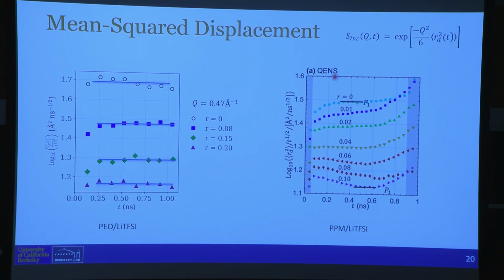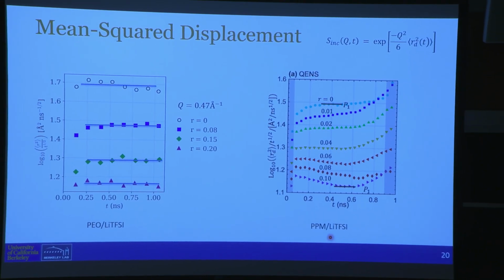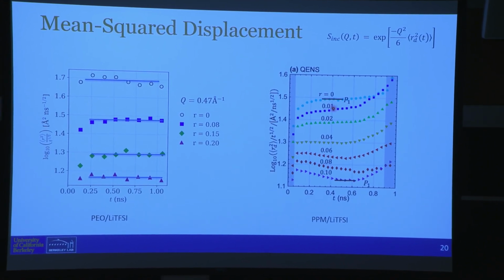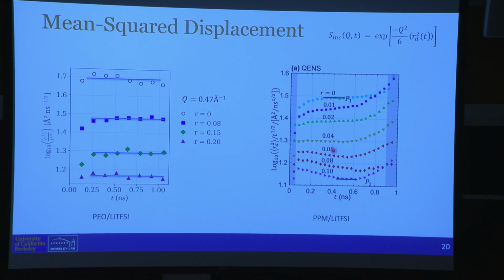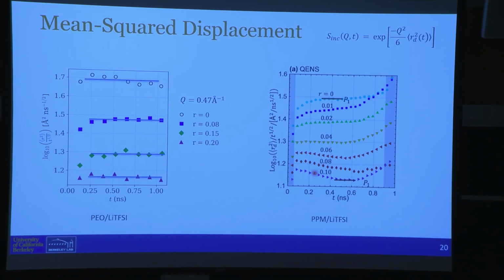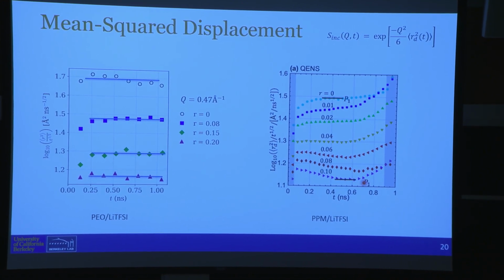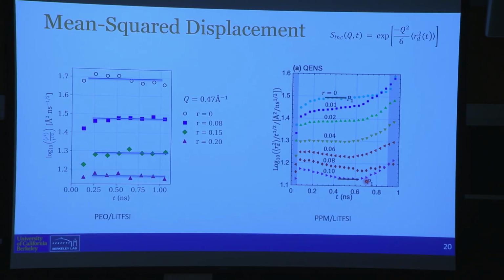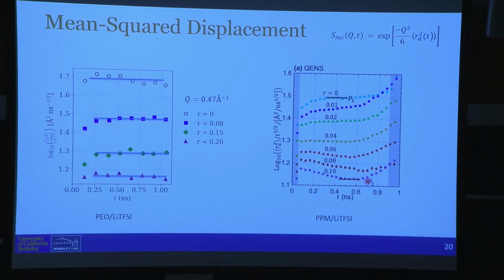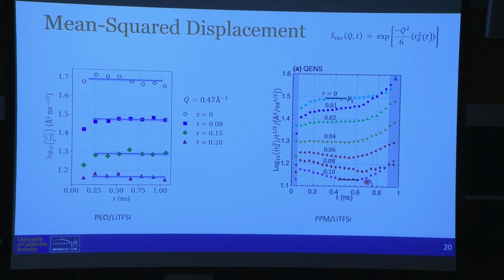When we did the same experiment on PPM, as concentration increased, we saw something weird, which is that instead of the plateau, we started getting a trough, and the plateau was pushed to higher times. So the mean square displacement actually goes as a quarter, not a half power, in that early time.